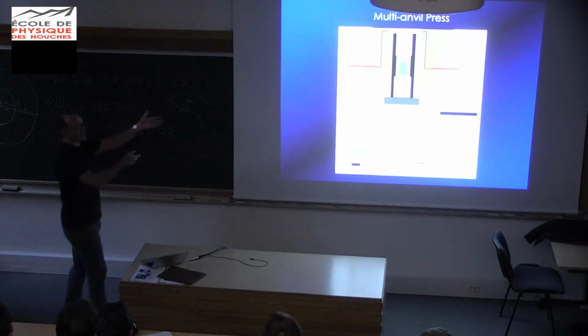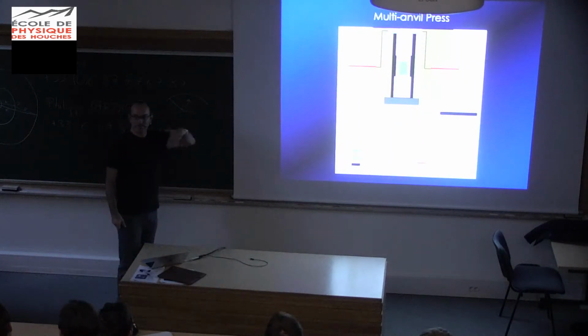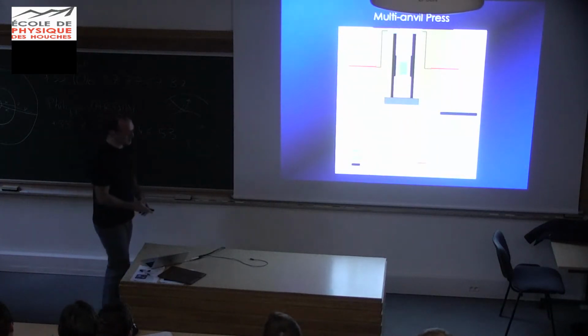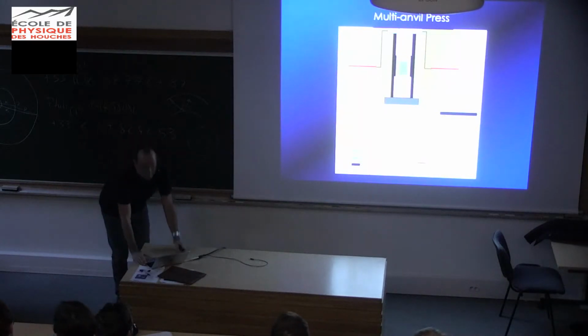Yeah, because as soon as you get to the pressures where this thing is operating, graphite turns to diamond. We're all very sad, right? Well, actually, for the sake of the experiment, you're sad. Diamond is an insulator, and it just stops heating. It's actually pretty impressive when you see it happen once, and then you hear a big pop.